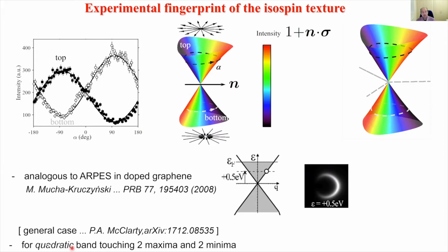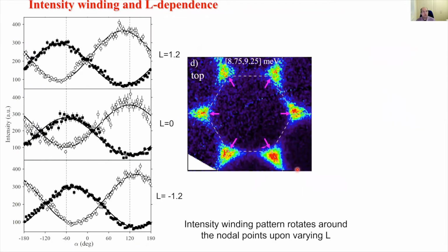And in fact, there could be other more complex situations. For example, if one has quadratic band touching, where these bands are quadratic and not linear. And in that case, one expects a more complex periodic pattern as a function of angle with maxima, minima, maxima, minima. So multiple maxima and minima. So now I want to show that rather similar features also happen in high energy excitations in this material, not just for magnons.